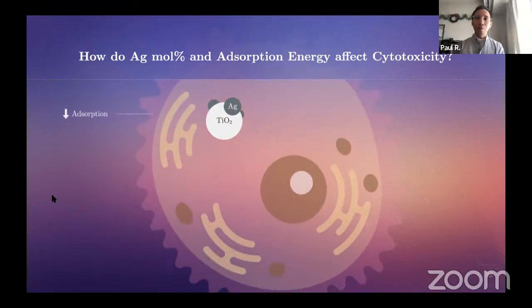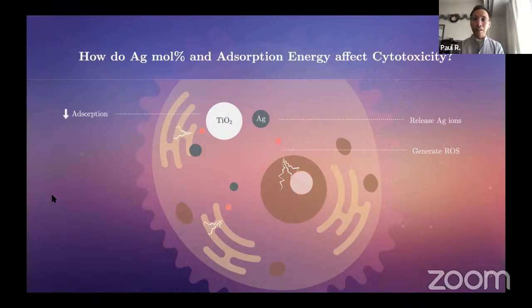Because of low absolute adsorption energy, the TiO2 cluster becomes less stable, and thus Ag nanoparticles can detach from the TiO2. These Ag nanoparticles can then release ions, which in turn generate reactive oxygen species, or ROS, and this ROS can lead to DNA damage, unregulated cell signaling, and cytotoxicity. So this explains how adsorption energy affects cytotoxicity.